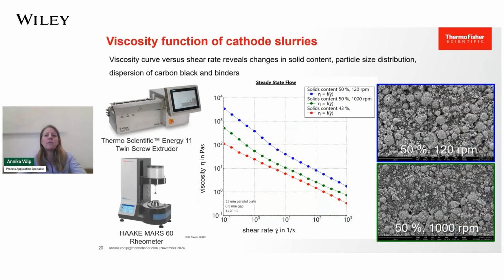This example here shows the viscosity versus shear rate of an aqueous LFP-based cathode slurry with 43 and 50% solid content, respectively, mixed with a lab-scale twin screw extruder at different screw speeds, namely 120 and 1000 RPM. Viscosities were measured in a Haake-Mars rheometer with 35 mm parallel plate geometry in a steady rotational shear deformation.